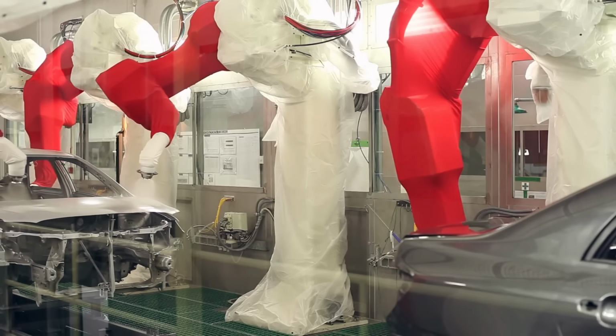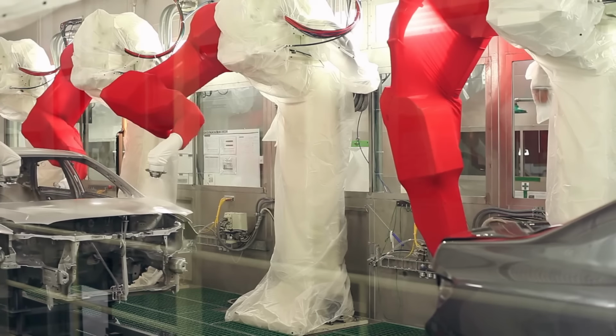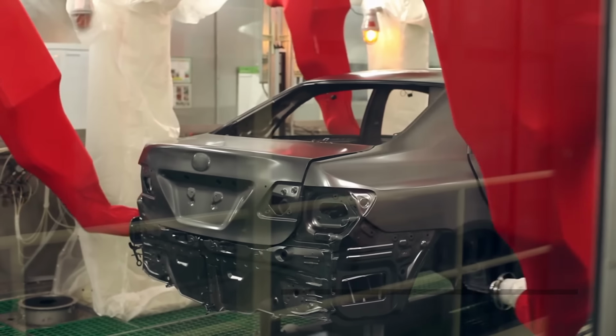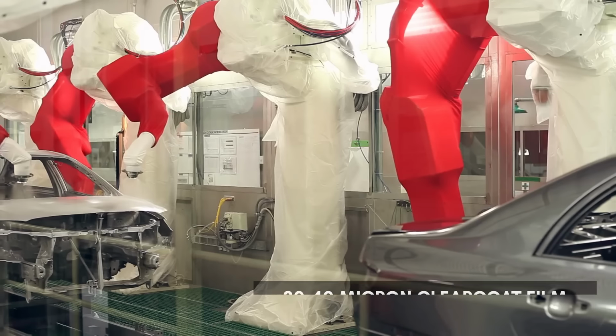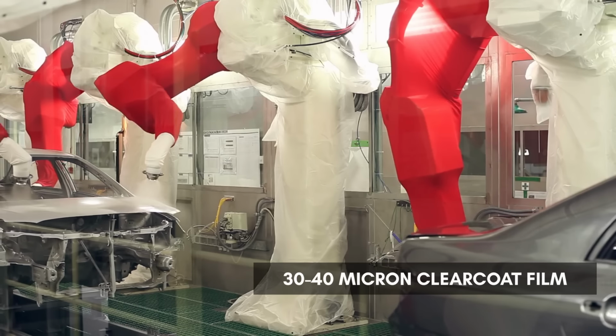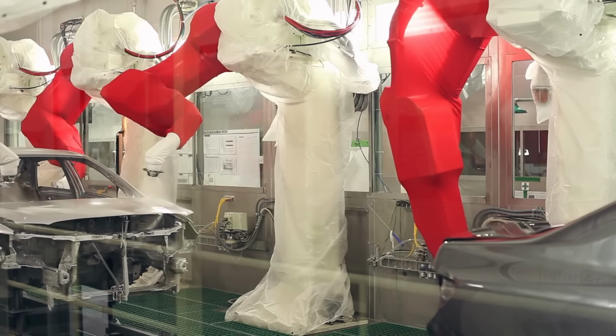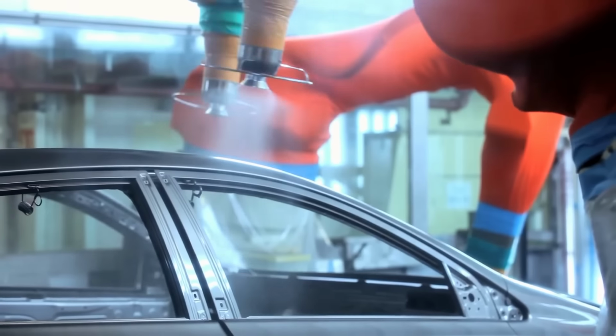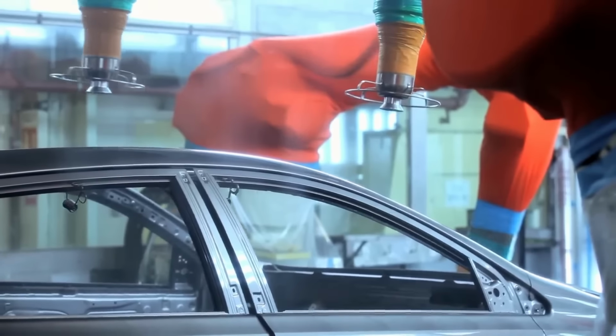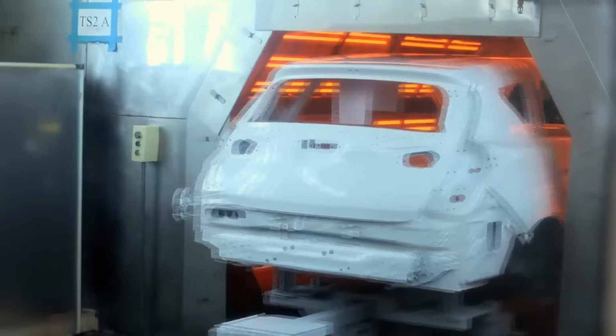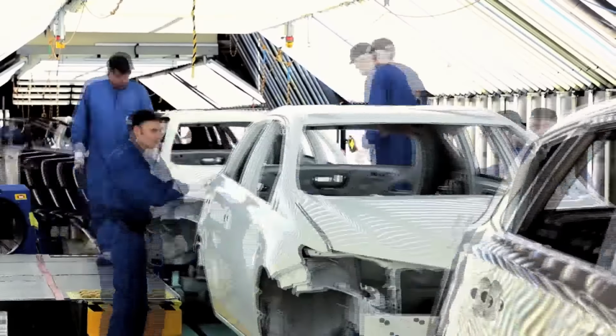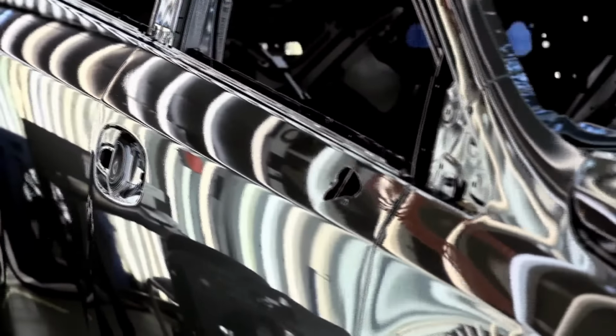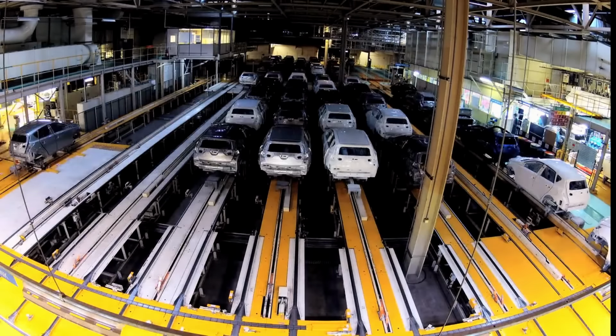In the final 2 steps of the body coating process, the top coat is applied. The base coat containing the pigment is first applied in a thin film of just 15 microns, followed by a 30 to 40 micron thick clear coat. The clear coat is applied after a brief flash-off period after the base coat, and once application is complete, the entire vehicle is baked at 125 degrees Celsius or 257 degrees Fahrenheit for 30 to 40 minutes to accelerate curing.